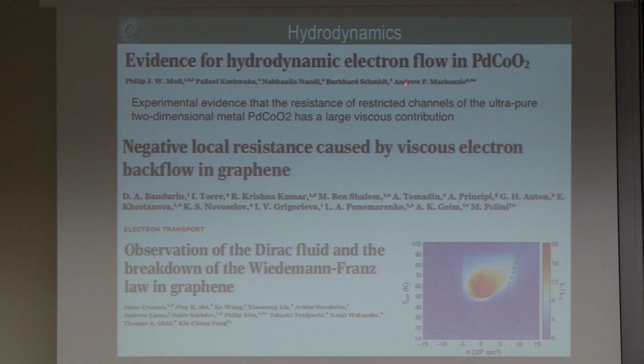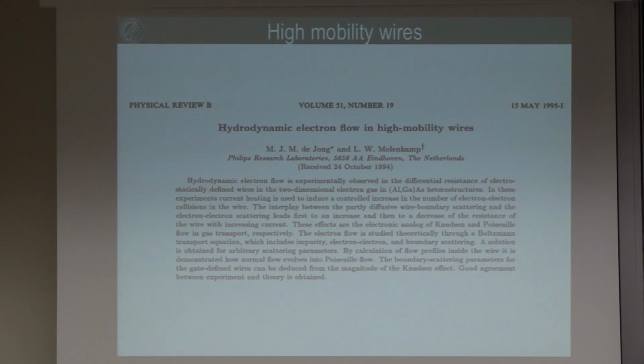And here Andy saw a dependency, which is interesting, of the width of the crystal on a mesoscopic scale. And this hydrodynamic electron behavior, why I like it especially, goes back again to very old theoretical work from Steve Kivelson. And the first measurements were done by Laurens Molenkamp. He measured them in, I think, gallium arsenide heterostructures. And here you see the connection, which I think is there. So they found hydrodynamic electron flow in high mobility wires.